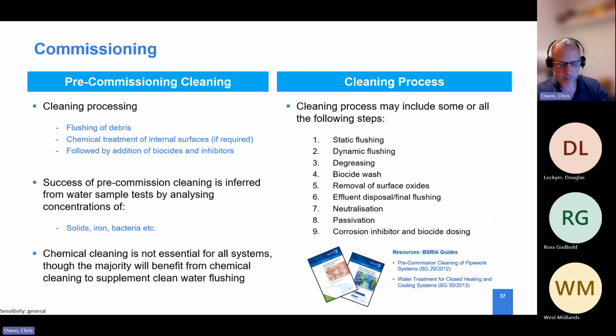There's a big debate going on at the moment about what's the best way of commissioning, whether it is with chemicals or with remote monitoring. We like both, because commissioning with chemicals means that you're cleaning the inside of the tube. If you're using biocide washes or inhibitors, you're adding chemicals which are going to mitigate the risk of bacteria, which can result in corrosion. However, if you've got real-time monitoring, you're collecting data which allows you to ascertain whether something has changed in your system, and it might not be down to pipework. It could be down to something else which has either failed or some other retrofit work which has added more oxygen into the system. So a mixture of both might be quite beneficial.